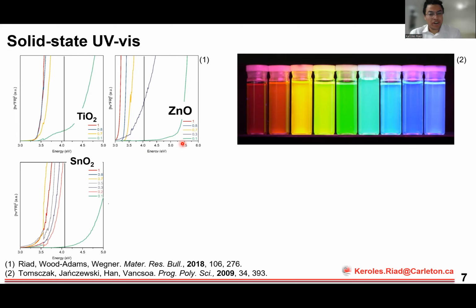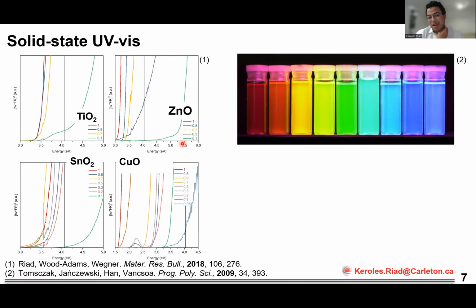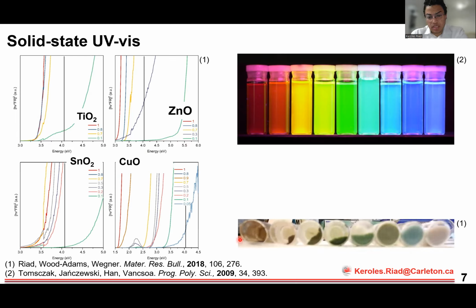So they're visually boring, and I got jealous and decided to make copper oxide quantum dots, because at bulk size, copper oxide is actually in the dark red region of light. And so the increase in band gap energy from the quantized effect would also translate to a color change, which is exactly what you see here. The bulk copper oxide is dark red, and as you add silica, the crystal size decreases, you have the increase in band gap energy, which translates to a change of color into green, blue, all the way to white once that band gap energy goes into the UV region of light.